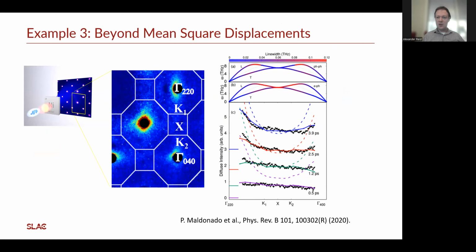Finally, we're also able to make momentum-resolved measurements of phonons. In between the Bragg reflections that we get from a typical diffraction pattern, this is a diffraction pattern on nickel, and here we've zoomed in and changed the color scale to remove these reflections. What you see is intensity appearing in between the peaks. This is the thermal diffuse scatter. This is the scattering of electrons from phonons.